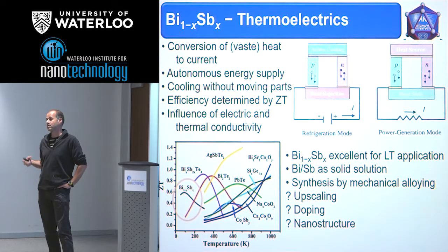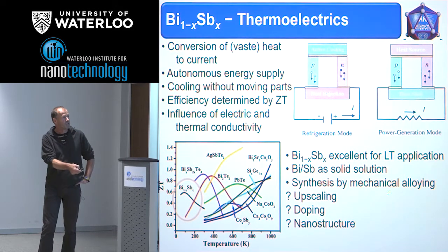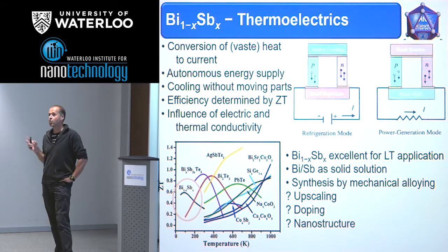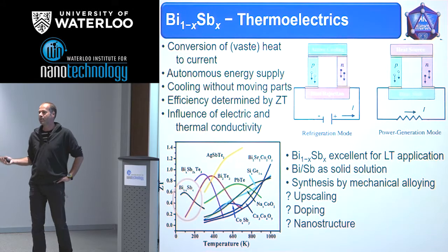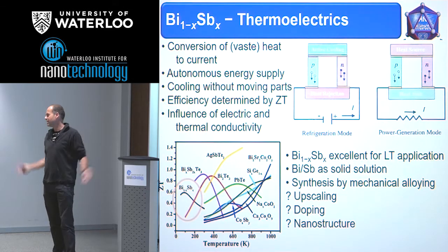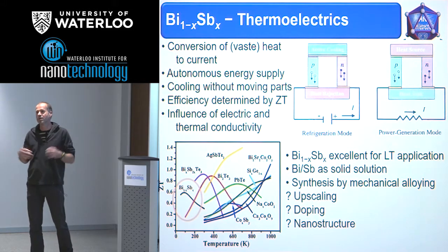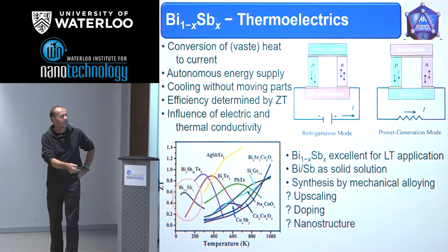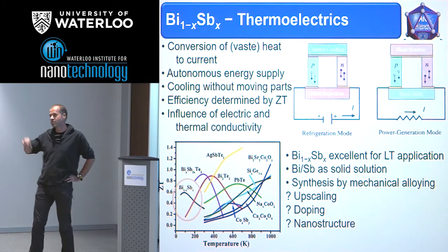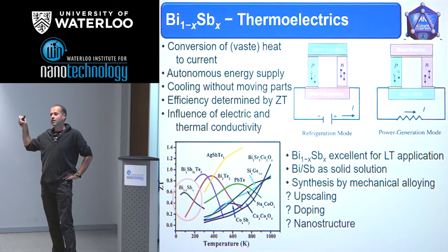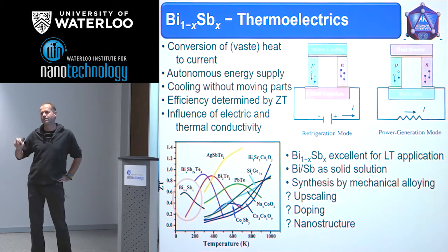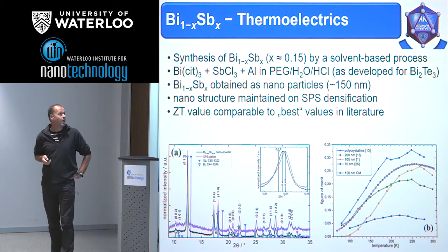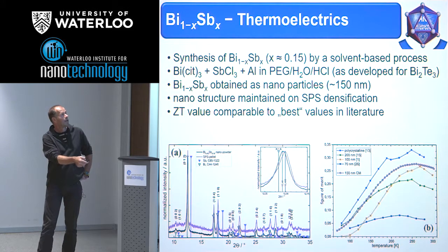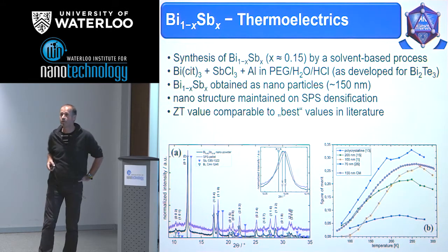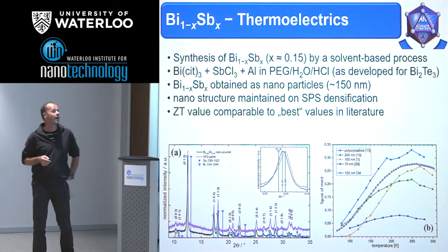Bismuth and antimony make a solid solution, that's not a problem, but the synthesis is usually done by mechanical alloying, and these processes are quite simple, but it's difficult to do a scale-up, because mechanical alloying in upscaling means you use several of the mills or larger mills, and that's not very good. And the doping is also a little bit of a problem, and the production of a nanostructured material, which is important for the lattice part of the thermal conductivity, is very difficult to do in a well-defined way by mechanical alloying. Well, we were able to synthesize the system with about 15% of antimony, which is the optimum for the ZT value, by a solvent-based process.